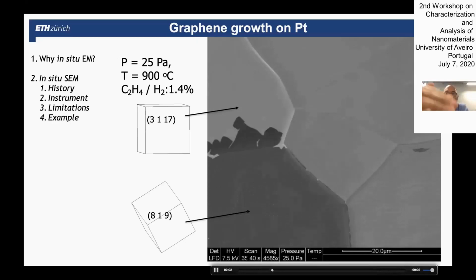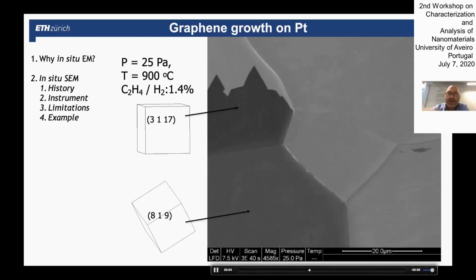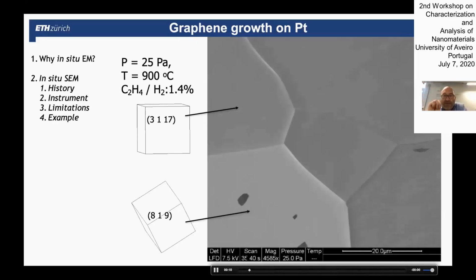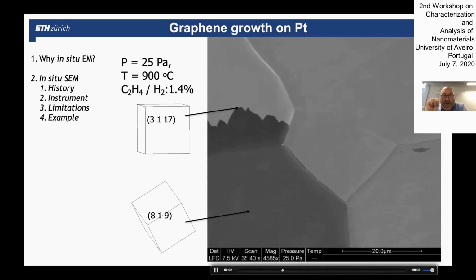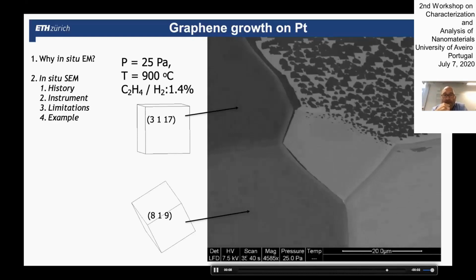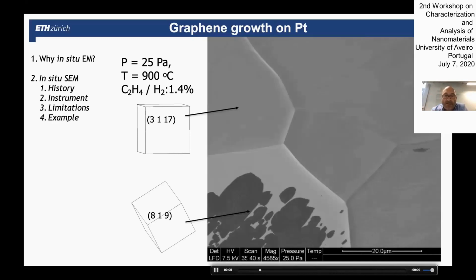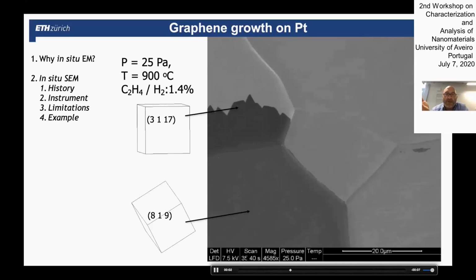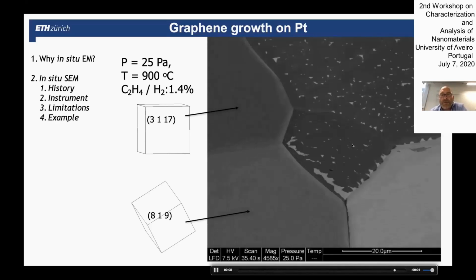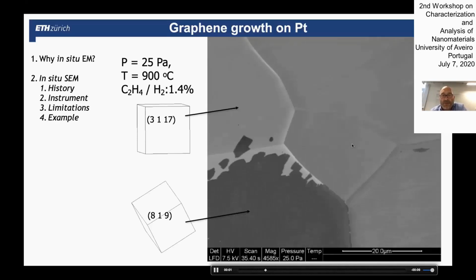seconds per single frame. And I'm running these videos at like 20 frames per second. So it's really sped up a bit. The only thing we varied during this experiment is the pressure of the ethylene. So at low ethylene pressure, only this bottom and the left grain is active. And then in the later stage of the video, we increase the ethylene pressure. And when we increase that, then the other grains also started to nucleate graphene. So we only played with the chemical potential of the ethylene.